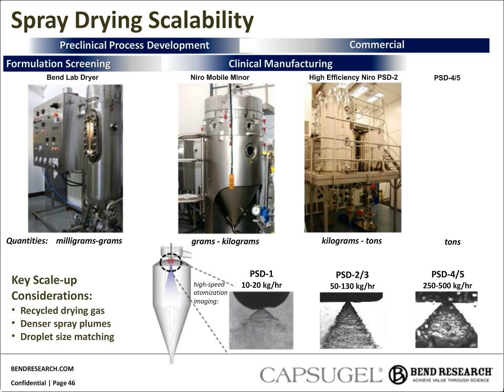So beyond the PSD2, we also have experience defining processes and scaling up to PSD3, PSD4, and PSD5 scale spray dryers. So by matching the droplet size and the drying rate or thermodynamics across each scale, the spray drying process can be easily scaled up from screening milligram quantities up to metric tons. There are two main considerations for matching the droplet drying rate or thermodynamics. One is whether it's an open or closed loop. In smaller units, the drying gas is not commonly recycled, and the smaller dryers often operate in open loop, while in larger dryers, the drying gas is recycled through the condenser and back into the drying chamber.